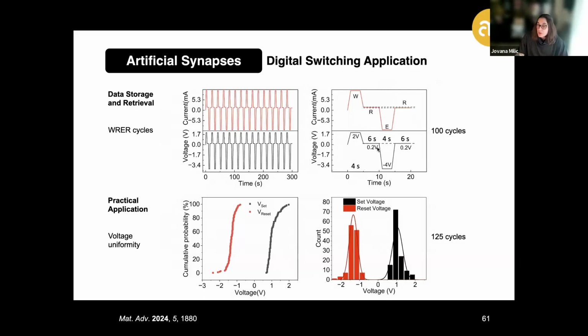Using, for example, the biasing or pulses at 2 volts for 4 seconds to write information, followed by small pulses of around 0.2 volts for 6 seconds to read the information, erase them at around -4 volts for 4 seconds, and then reread the input again at 0.2 volts for 6 seconds.